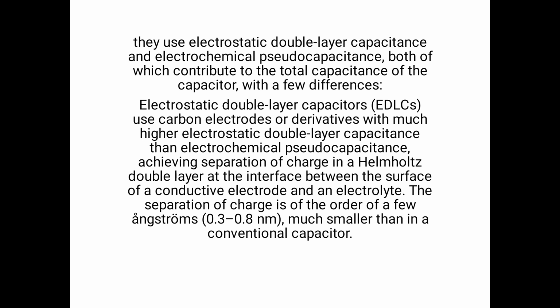Electrostatic double layer capacitors, EDLCs, use carbon electrodes or derivatives with much higher electrostatic double layer capacitance than electrochemical pseudocapacitance, achieving separation of charge in a Helmholtz double layer at the interface between the surface of a conductive electrode and an electrolyte. The separation of charges is of the order of a few angstroms, 0.3 to 0.8 nanometer, much smaller than in a conventional capacitor.